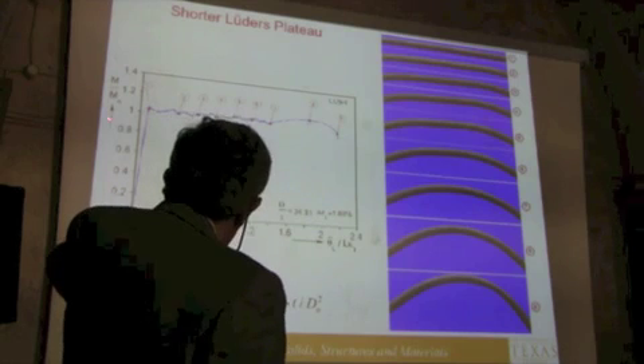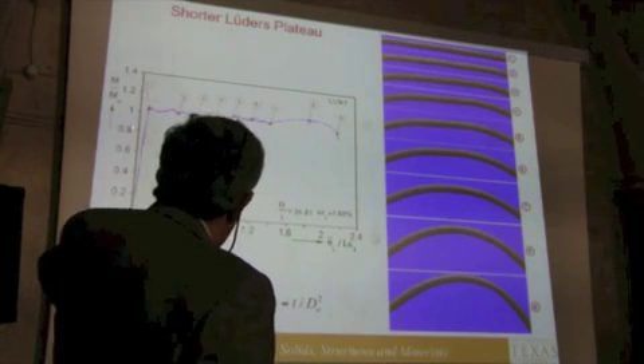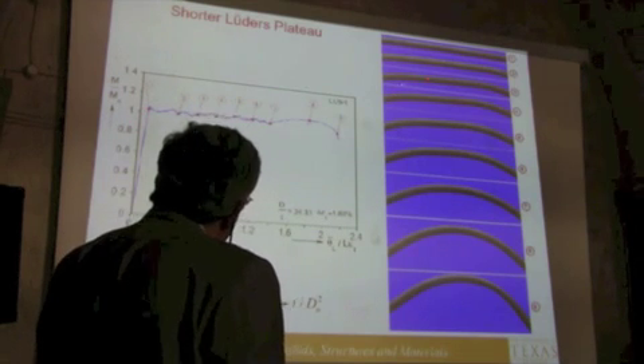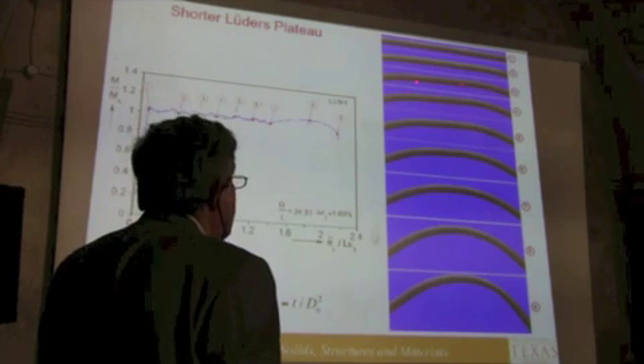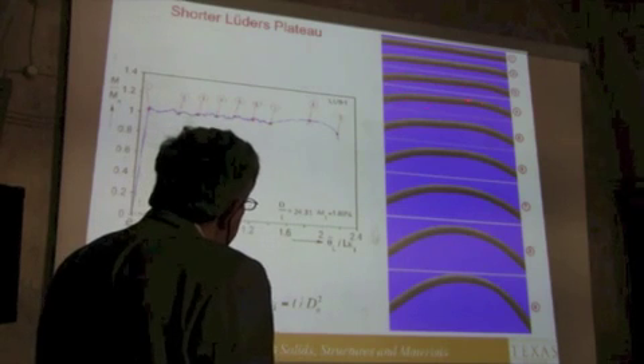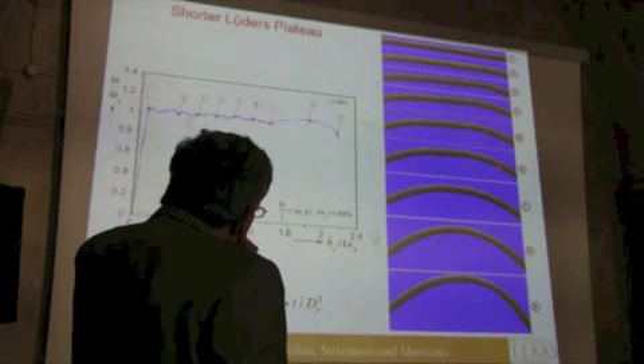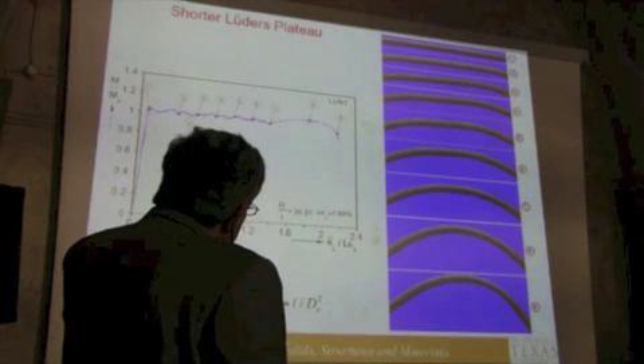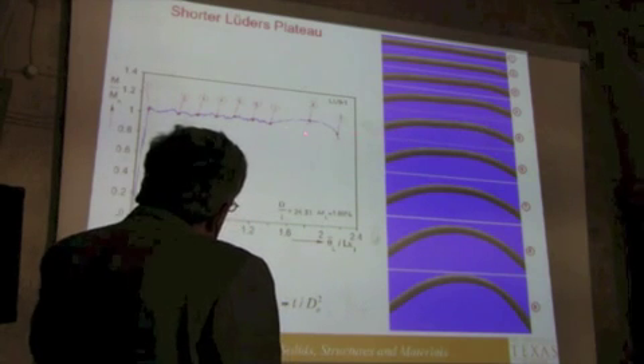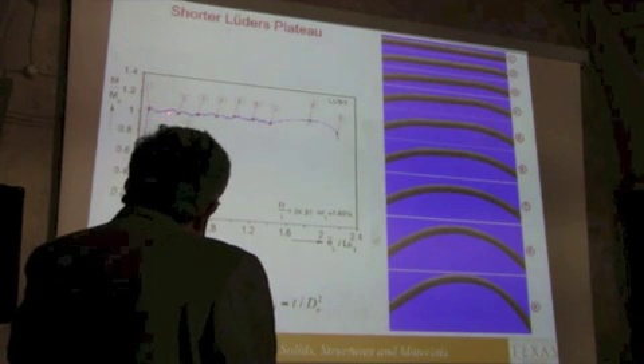Remember, the material has a plateau in the stress-strain curve. It became a plateau in the moment. And during this plateau, what happens is that we have a localization, but it's a structural localization. The curvature gets larger in these two locations, and I have coexistence of high curvature and low curvature. This curvature here is at this point, and this curvature is at this point.